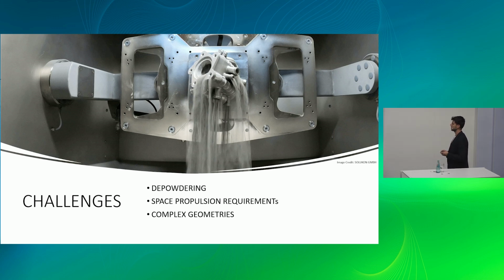It's the most critical step in the post-processing because if one of these cooling channels would be blocked, the consequence, obviously, is that the fuel would not flow anymore through it. So the cooling functionality is lost completely. You have a heat buildup, which would, in the end, in a hot firing, lead to a melting of the engine, if not explosion. So that is very, very critical. To check that, at the moment, we're doing a CT scan afterwards to be very sure that we put only flawless parts on the test bench. It's not only about our parts. If a test bench gets damaged or destroyed, that is something you don't want to have in your finance records.